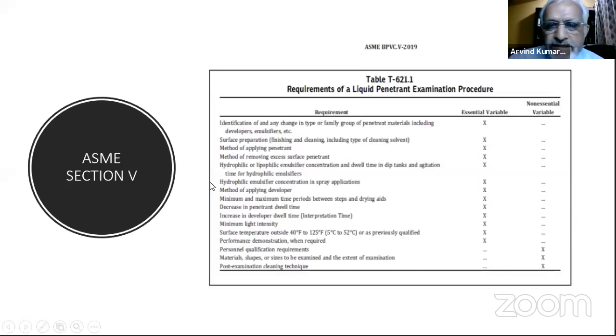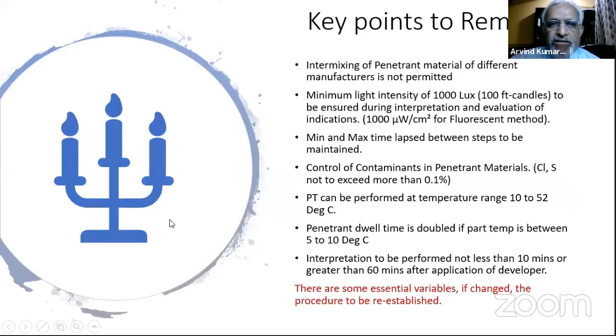Now, because this extract did not come very clear, for each method I have prepared the key points which we should remember while we are performing PT. It's a summary of all what we discussed, and the important things which we should not miss out during performance of PT are listed here. Intermixing of penetrant materials of different manufacturers is not permitted. The code doesn't allow that you have a penetrant of one manufacturer and a developer of another manufacturer, or I have a little left penetrant of one manufacturer, I add a penetrant of the other manufacturer in that. These things are not permitted. It has to be of one manufacturer only.